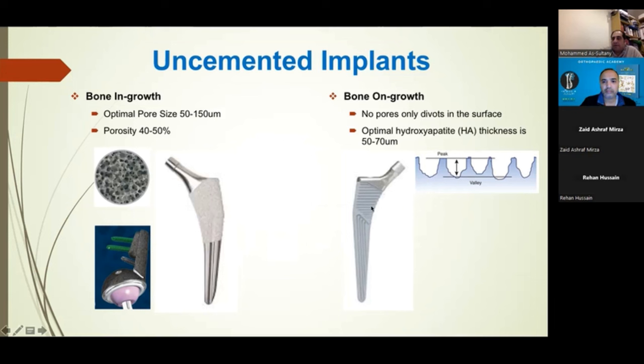Bone ongrowth is slightly different in that you have peaks and valleys in the material, and the idea is that the bone grows onto this surface, such as hydroxyapatite, which needs to have a certain thickness. So you have no pores, but you only have divots on the surface. And the idea is it grows in and out, and it creates a friction in that surface to prevent the motion. Again, achieving primary stability by that means.